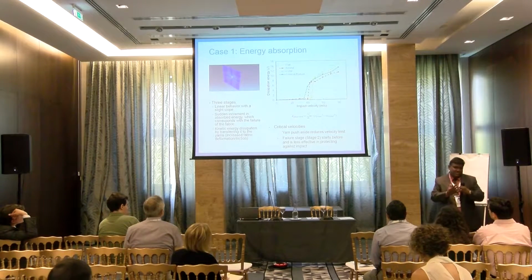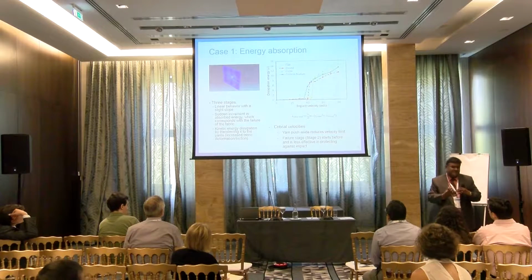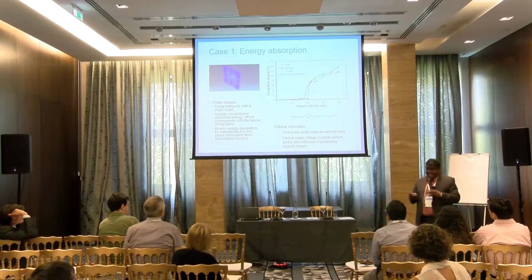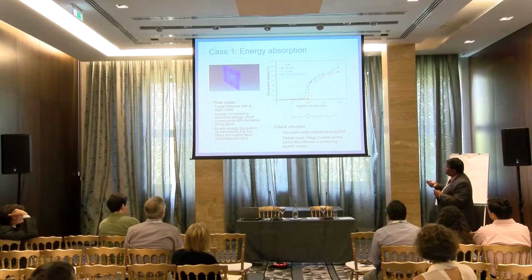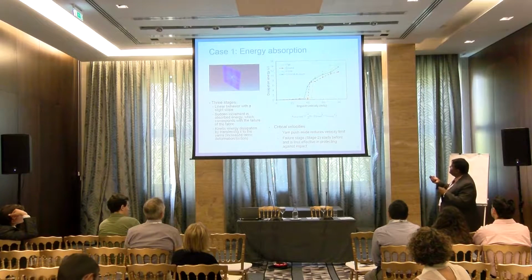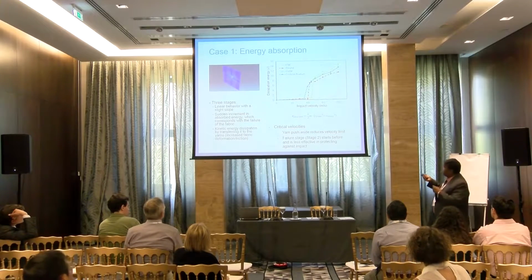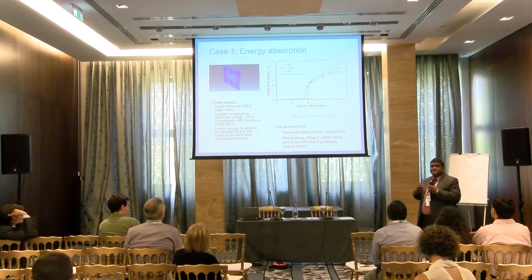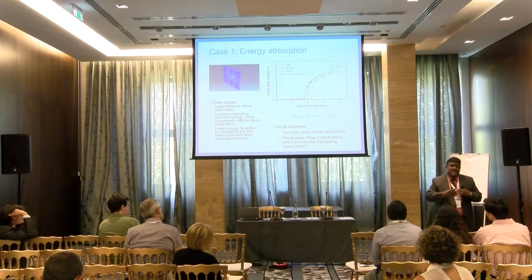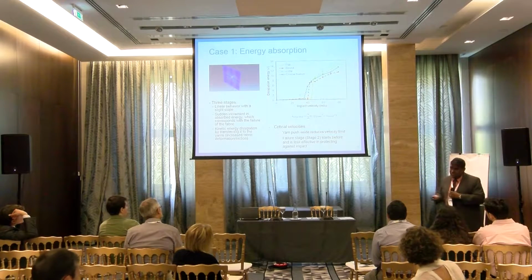So there are two modes. There's a friction coefficient, so the fibers rub against each other, so that's one mode of energy dissipation, and the fibers can fail if the ultimate strength is exceeded, like in a spring mass system. You just break each fiber, and that will cause an energy dissipation as well. And then we hit a sudden increment in absorbed energy, which corresponds to significant failure or damage in the fabric. And then in this part the fabric has been penetrated, so there is not much dissipation by damage anymore, but there is kinetic energy dissipation by transferring to the yarns. The projectile transfers a part of its kinetic energy to the yarns, which is then dissipated by friction and elastic deformation. And if you include plasticity in the fiber, it could be plastic dissipation as well.